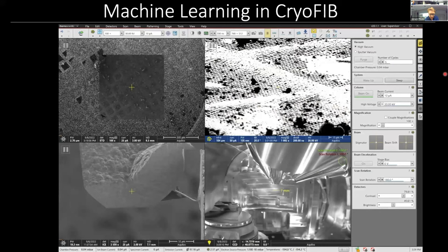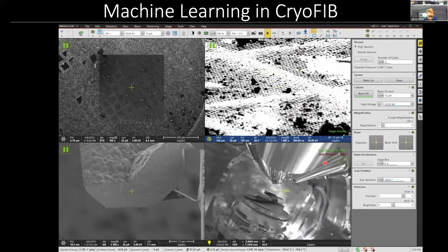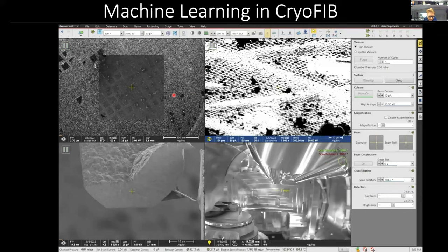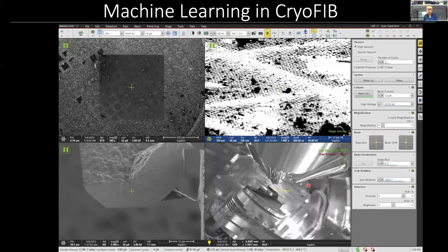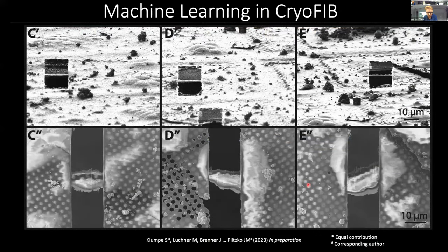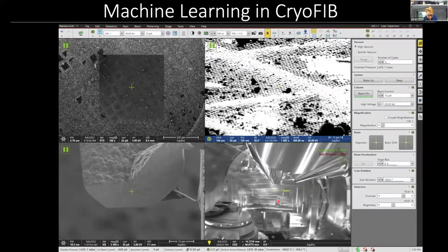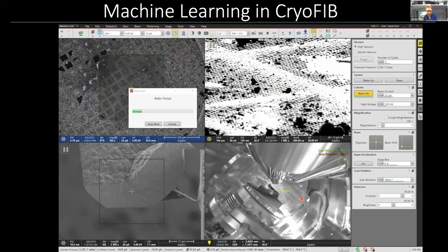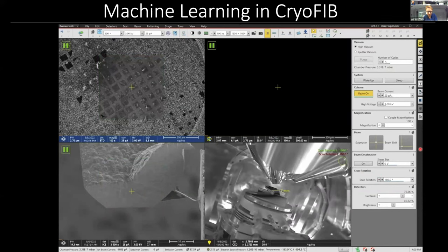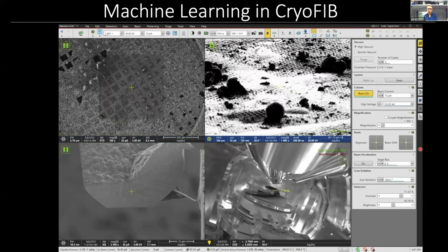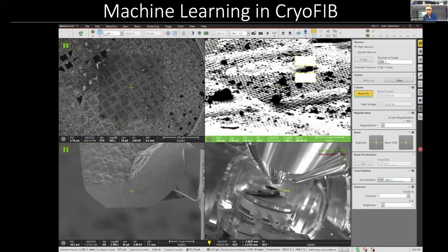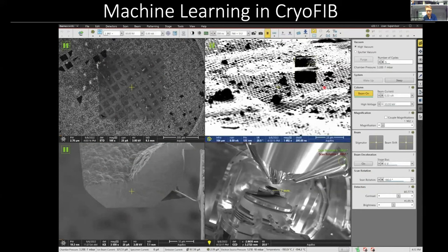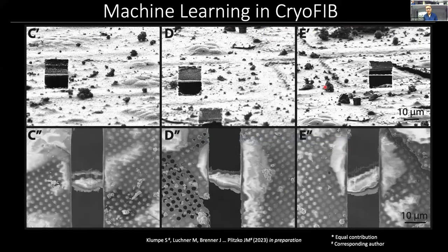And the way this would look on a real microscope is that on the top left, we would have the SEM view, on the top right, the FIB view, and on the bottom right, a little camera inside the chamber. And what we're going to do is basically move to the correct position for depositing a protective layer of GIS platinum inside the chamber. As you can see here, this little needle coming in, and then we screen the grid and the instrument without any user intervention, our workflow will decide on positions to create these lamellae, as you can see here on the top right. And just a bunch of these examples, as you can see here.